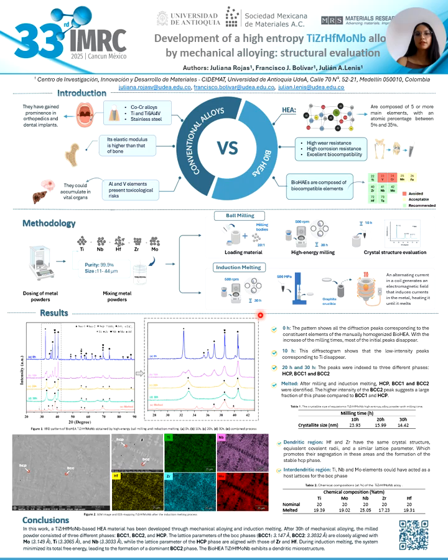Image 1 shows the results of X-ray diffraction of the alloy obtained by mechanical alloying and induction melting. The blue patterns show all the peaks corresponding to the constituent elements of the alloy, such as titanium, zirconium, molybdenum, hafnium, and niobium.